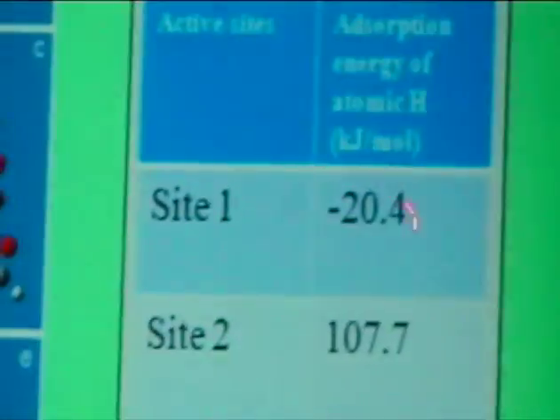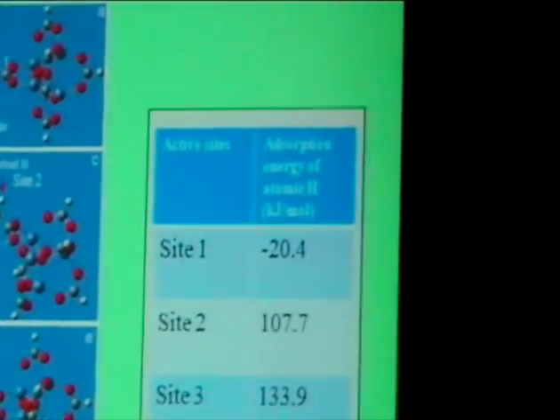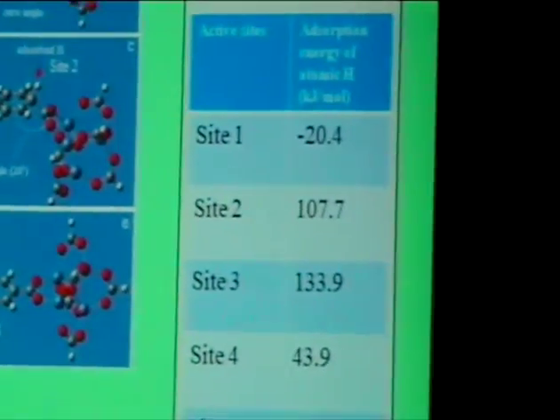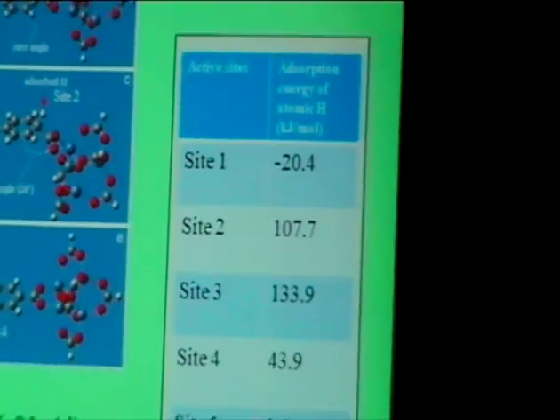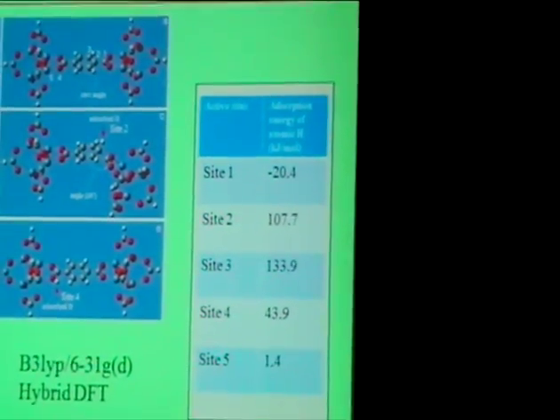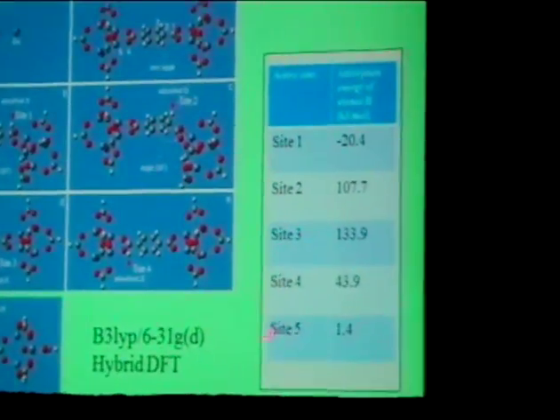As we did the calculation, we can see that for active site 1, they get a negative stability energy. That means the oxygen is not active to absorb hydrogen, because if you put hydrogen on this site, you will increase the energy. So that one cannot hold hydrogen. For the others, you can see the active site 5 is here. This is also a very weak interaction, because it's atomic hydrogen on this active site.